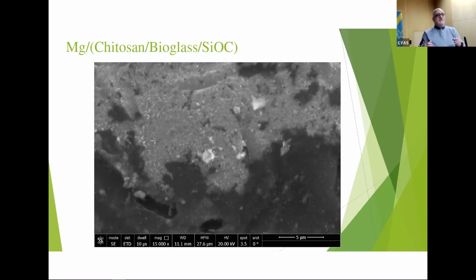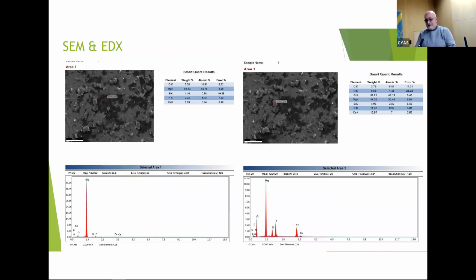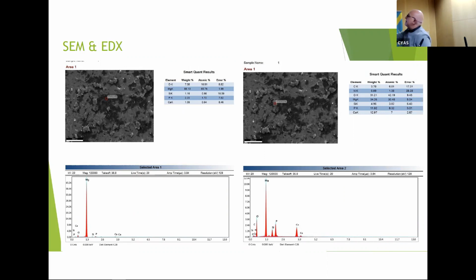That's what we call the coating morphology. That's the big picture under the microscope. We are seeing this kind of structure, so it completely covers the surface of our magnesium. And then here, if I need to get information about, for example, this small zone or area, what about the composition of this small zone? That's by EDX, inside the microscope. We use X-ray to get information about what kind of coat we have in this area.